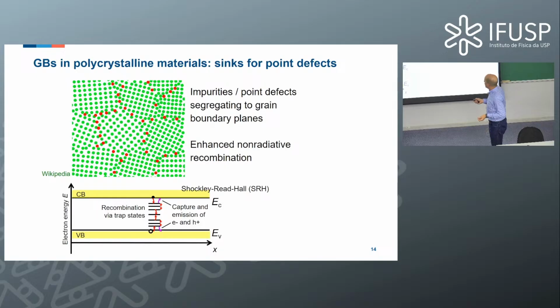Okay, so if we now look at the situation, again, this is segregation of, let's say, impurities, point defects. Yeah? We have enhanced non-radiative recombination. This is one important detail of any grain boundary. Yeah? So you always have a higher density of defects that contribute to a higher rate of Shockley-Read-Hall recombination. This is a recombination describing recombination of excited charge carriers via defect states that basically capture the charge carriers, right, until they meet one another.